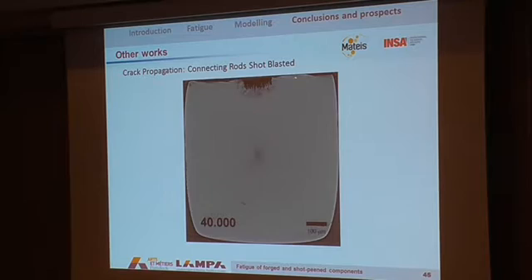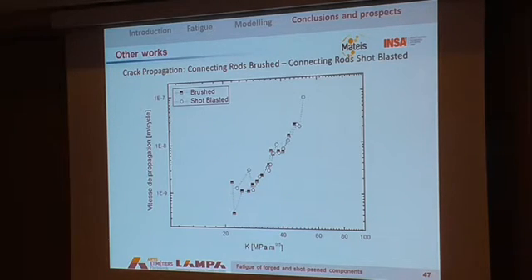What you see is the development of the crack front as a function of the number of cycles. And by doing so, we are able to investigate the crack growth rate as a function of the stress intensity factor. And what is very surprising is that we don't observe any effect of the residual stresses on the crack growth.